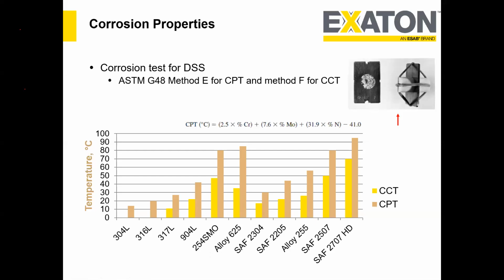I would say no. I'll also explain later why no. Don't always check only the critical pitting temperature. Yes, it has a very good pitting resistance, but it has a very bad resistance to crevice corrosion. So the major failure of alloy 625 comes on the crevice, not on the pitting. When a component goes into seawater, or any application where chloride is present, it is not only pitting corrosion. So pitting and crevice are both equally important.